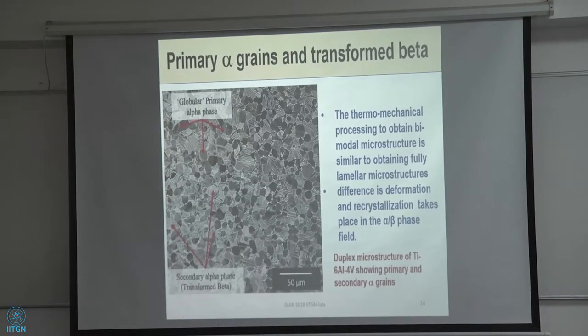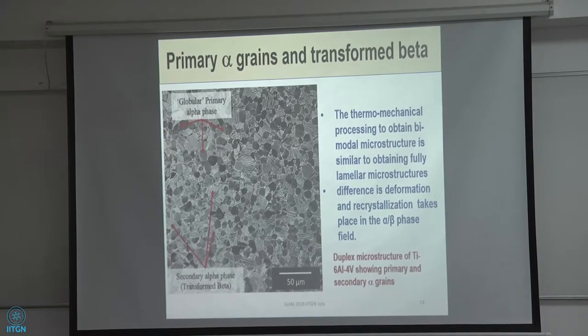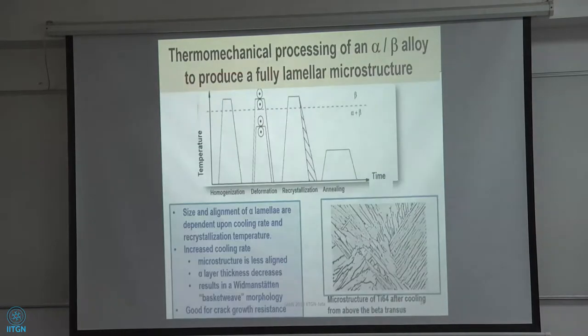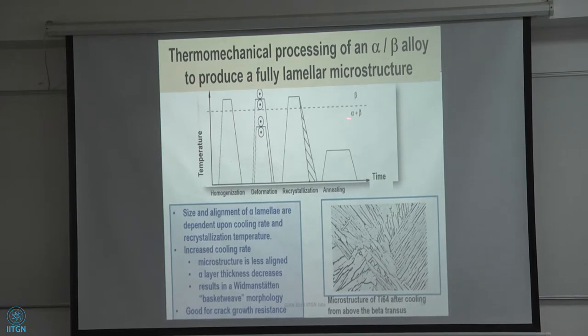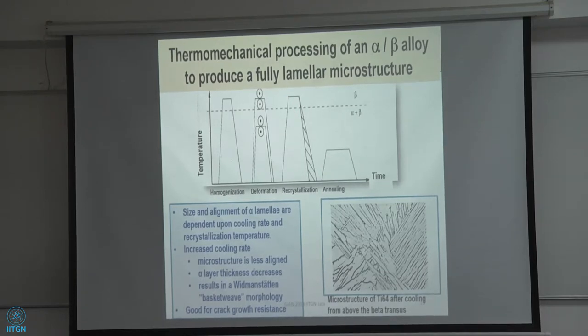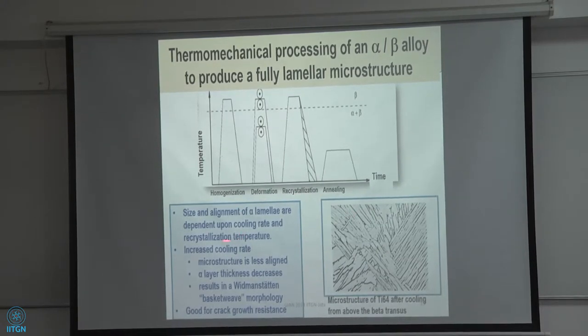More alpha volume fraction, more of this HCP volume fraction will be playing a role in the overall deformation, right? And the titanium alpha phase has three known slip planes, basal, prismatic, and pyramidal slip, which I'm going to show in the next picture. Okay, so there is your basal plane. That's a basal plane. Okay? And there is your prism plane, 10 bar 10.